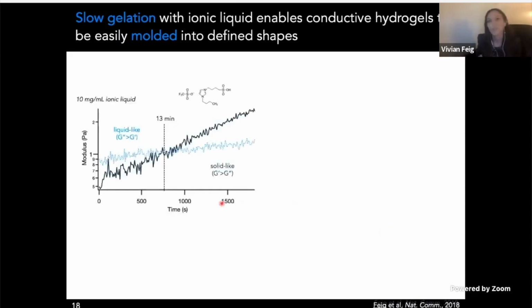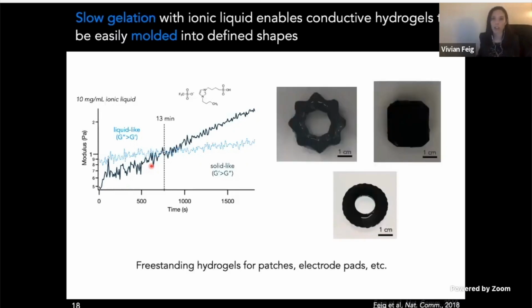And what we see is that there's actually a relatively large window of time where the loss modulus here in light blue exceeds the storage modulus, meaning that this mixture is behaving like a flowable liquid. And so this is pretty beneficial because it means there's enough time to take these precursors and pour them into different molds so that we can directly mold these highly conductive freestanding shapes for things like patches or electrode pads, which could be really useful for doing things like taking electrophysiological measurements throughout the body.